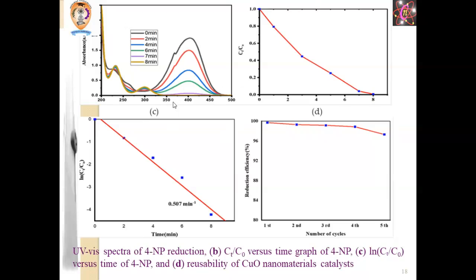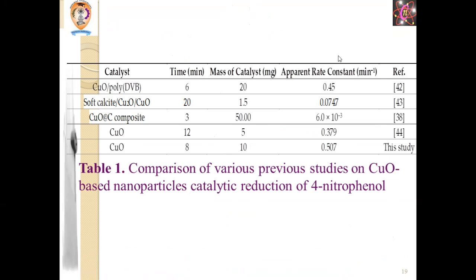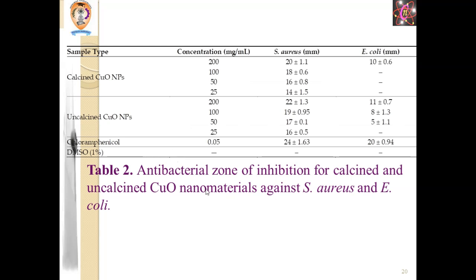So as you can see, this is a very important result, confirming our catalyst was highly effective in the catalytic degradation of the organic molecule. The results were summarized in this table, and we were lucky to find a very impactful result compared to the previous studies. And this is the antibacterial application of these materials, not only the catalytic application, but also the antibacterial medical